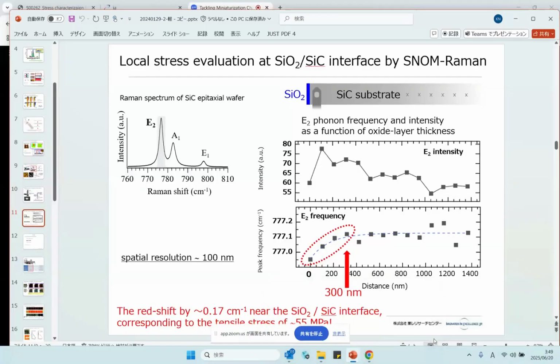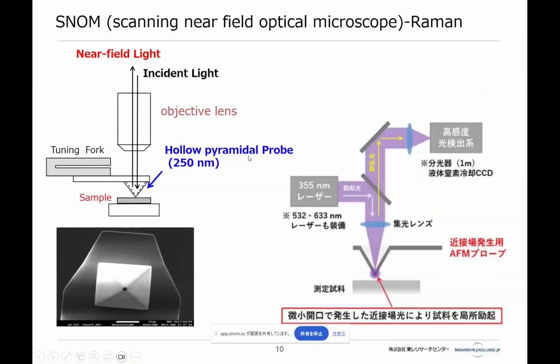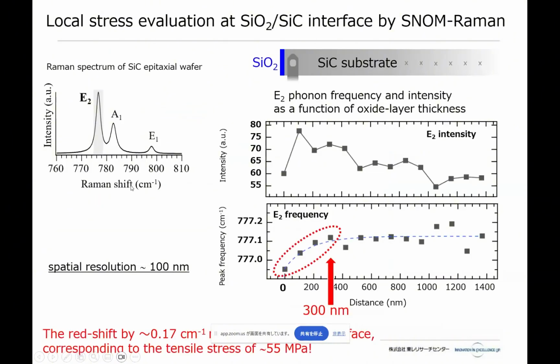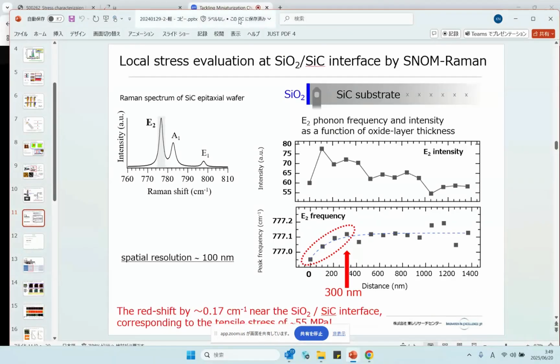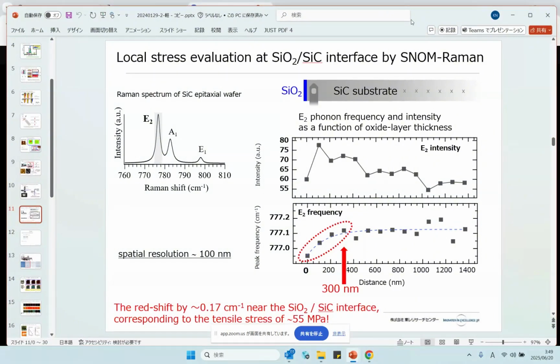Let me share my screen again. We also have this technique, SNOM-Raman. In this case, we also use this kind of needle-like probe. This probe has a small hole at the tip of the needle-like probe. Then we put light from the surface of the needle, and the light penetrated through this hole we use as an incident beam. So finally, we could get Raman spectroscopy with a resolution on the order of 100 nanometers. I think this technique is useful to characterize localized stress in the semiconductor.